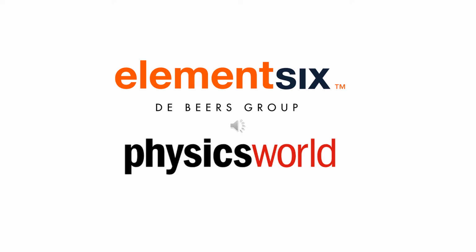So you've got this solid-state system, diamond. You've got this quantum spin, and this spin is pretty much isolated from the environment, which means it has very, very long decoherence times. People at Harvard have measured seconds or tens of seconds. So once you've initialized this state, it can stay effectively quantum for seconds. And in that time, you can do an awful lot of operations and manipulate it and get the benefits of what quantum gives you. So you've got this spin. It's very isolated, but there are ways that it can be interacted with.